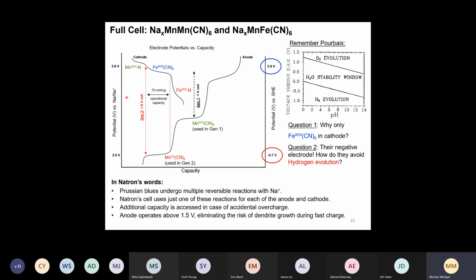So for sodium, it turns out that the difference is about 2.7 volts between sodium potential and standard hydrogen electrode. So if we convert those voltages, then the cathode would sit at about 0.9 volts versus SHE, and this low voltage manganese anode sits at about minus 0.7 volts. So what does that mean?